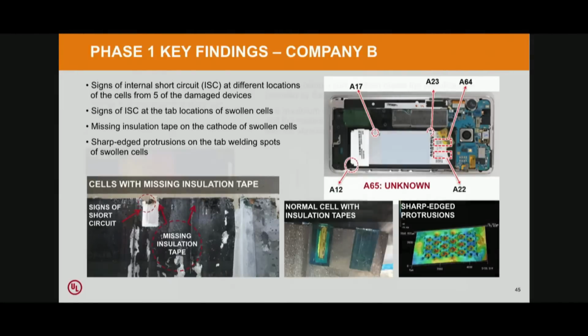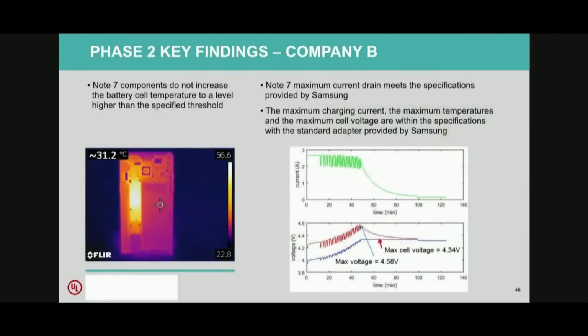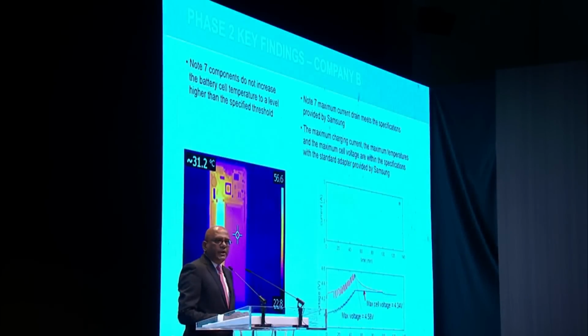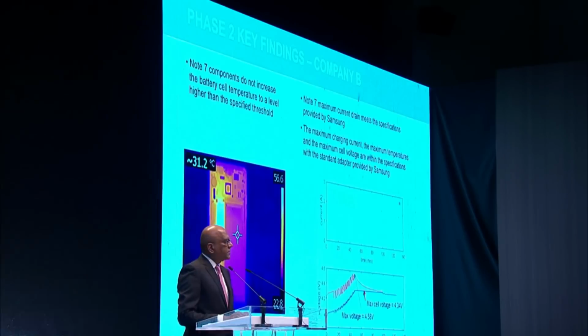Phase 2 had the following findings. It was clear that the Note 7 components did not increase the battery cell temperature to a level higher than the specified threshold, and that the current drain met the specifications as provided by Samsung.